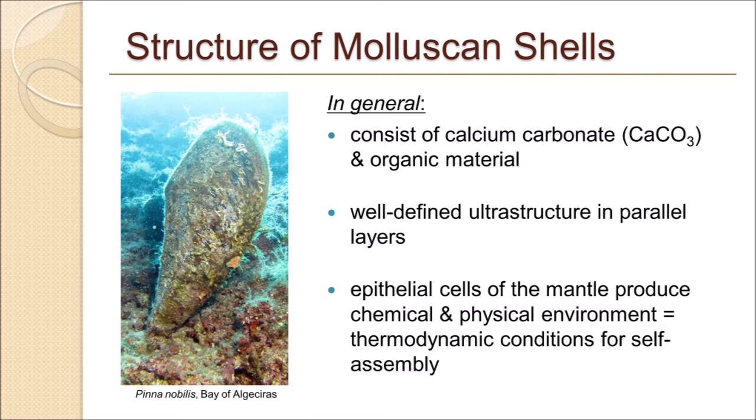The deposition of shell material, that is, the growth of the shell in thickness, proceeds on a purely organic layer termed periostracum, which covers the outer surface of the shell and serves as a template for the biomineralization process. The various shell ultrastructures are formed sequentially at the interface between the mantle tissue and the inner surface of the shell. The former provides all the necessary organic and inorganic precursors for the various structures to form. Hence, it sets the thermodynamic boundary conditions for self-assembly to happen.